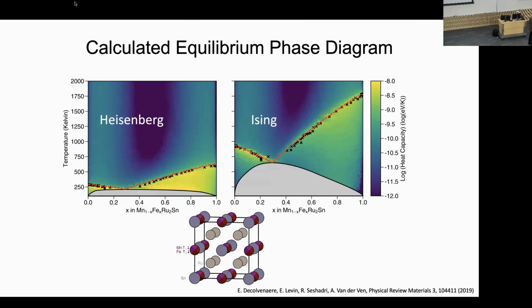So the manganese-rich wants to be anti-ferromagnetic, so the magnetic moments are opposite spins, and this is an anti-ferromagnetic phase. Over here, this is a ferromagnetic phase. This is where it's iron-rich. In that case, all the magnetic moments want to be parallel to each other. And then they disorder over here to form a paramagnetic phase. And there's a miscibility gap, and then these magnetic transitions appear to come together at this tricritical point over here. Now, this is where we combine chemical degrees of freedom and magnetic degrees of freedom.